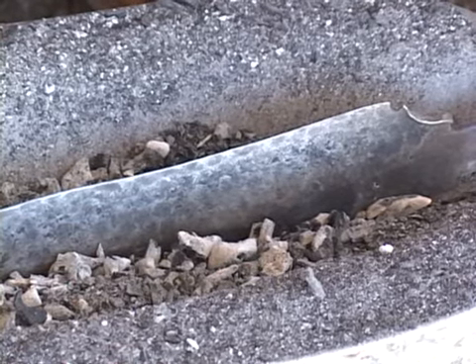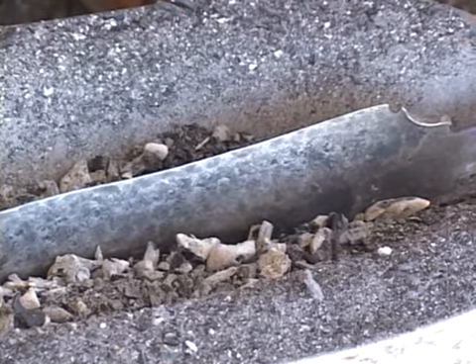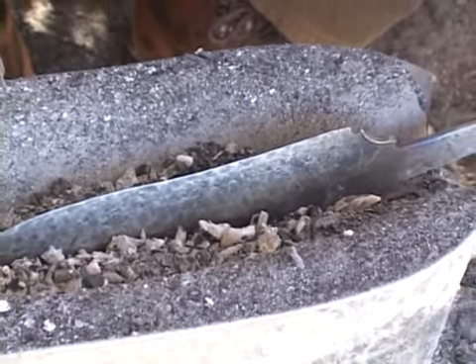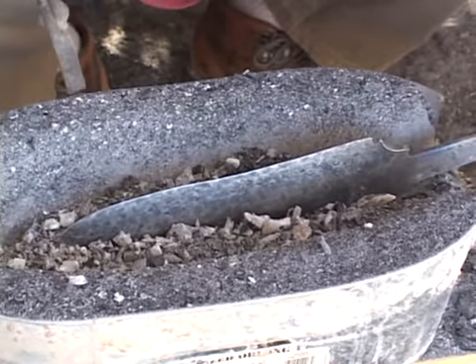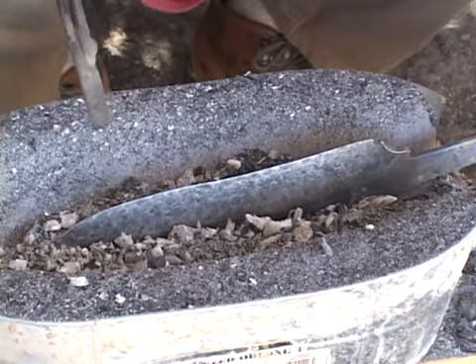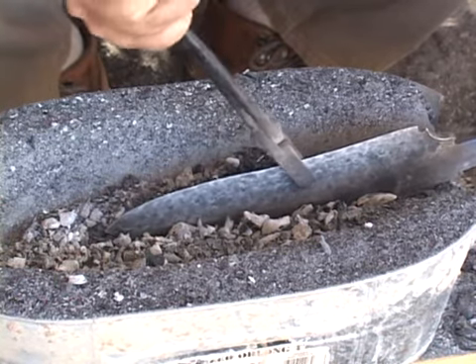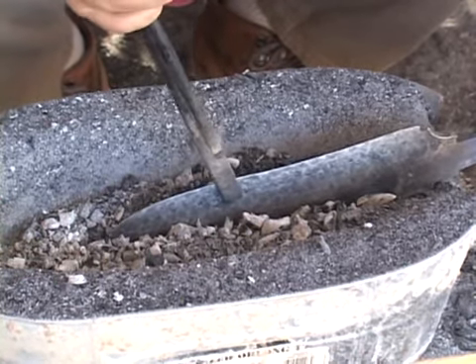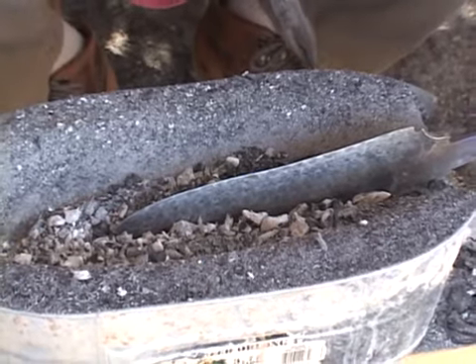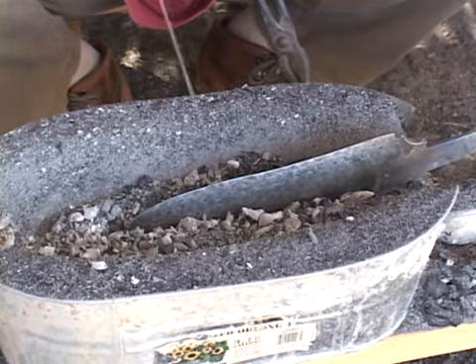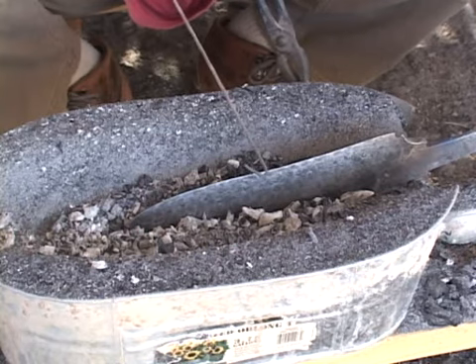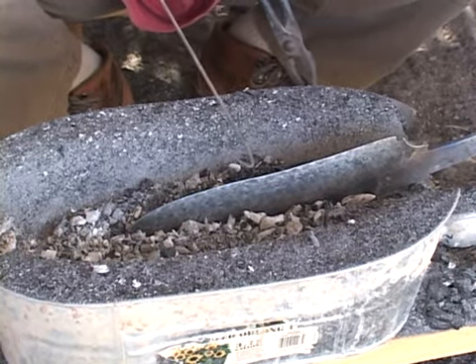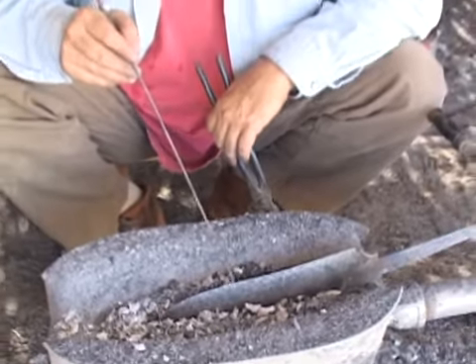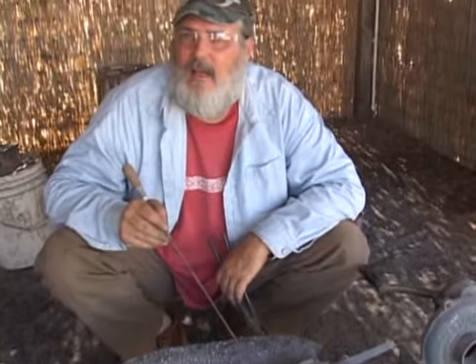So essentially what I'm doing with the tempering is drawing out some of the hardness, so it'll be able to be sharpened easily, and it won't chip when you're hacking away at some hard wood or anything like that. A good way of figuring out what kind of temper you need is just by practicing and experimenting with different edges. The way I did it was taking it to whatever colored temper, I tried all different kinds of temper colors, but I'll go to, say, a light straw, and then I'll go hack on a piece of ironwood for 10-15 minutes or something, and then I'll look at the edge with an 8x loupe and some strong light, and under the loupe you can see whether it chipped out or if the edge rolled.